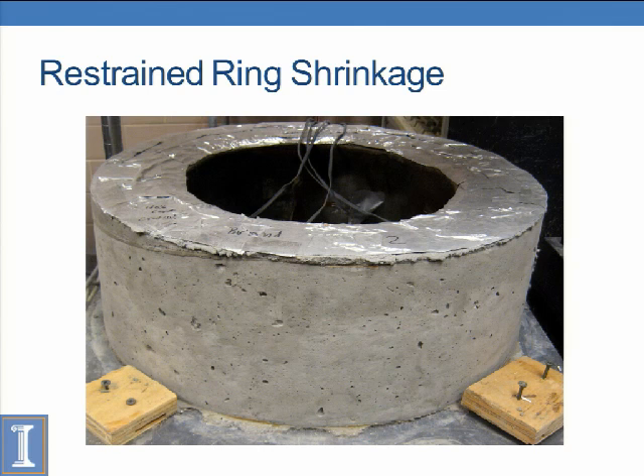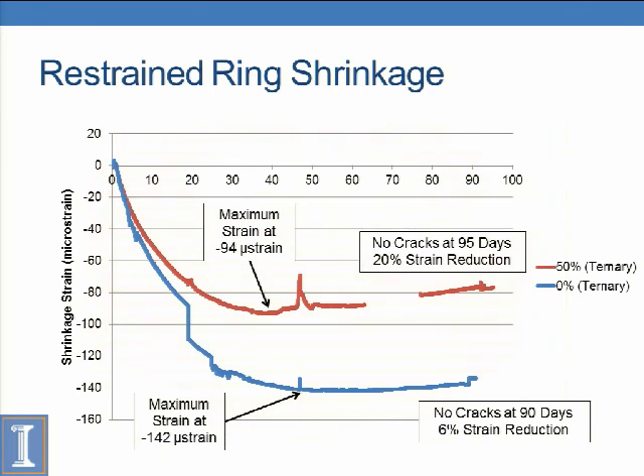Eventually, the test should tell you at some point the concrete strains will get so high that the concrete will crack. And that's pretty much what this test is looking for. You're measuring the strains, looking for when it will crack. Problem with this test is that our rings did not crack. So pretty much the only data we could get from this test was the shrinkage strains.